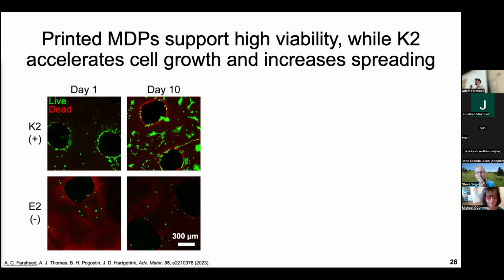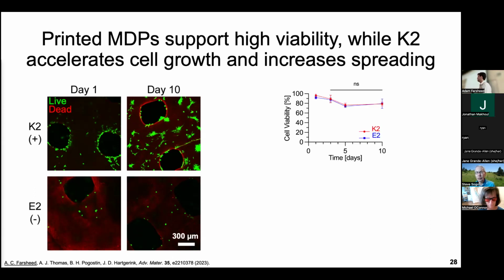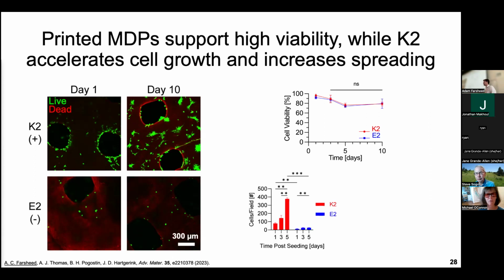And so we basically take a myoblast cell line, we put them onto our scaffolds, and we're looking at them at day 1 all the way up to day 10. And so these little green dots are individually each live cells, and red dots, which you won't see a lot of, are dead cells. And I want to point out 3 main things that we observed using our system. The first is that we got high cell viability regardless of whether we used K2 or E2. Independently, up to 10 days, the cells were surviving and happy for what we could tell. The second thing that we noticed is that while cells were growing on the negatively charged E2 material, the cells were growing at a much faster rate on the positively charged K2 material.